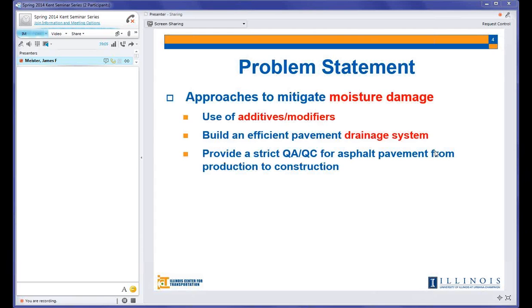For your knowledge, transportation agencies, when they face moisture damage or when they know that they have a moisture susceptible mix, they tend to follow one or more of the following approaches. Either they use an additive or modifier added to the asphalt mixture in order to enhance the bonding between the asphalt binder and the aggregate, so making it more moisture resistant. They make sure that they build an efficient drainage system. It's inevitable that we will, at the end, have moisture in the pavement. But the key here is that we need to get rid of that moisture as fast as possible. And also, it's good to have a strict QA/QC for the asphalt pavement, starting from the production at the asphalt plant toward the end, which is the construction.